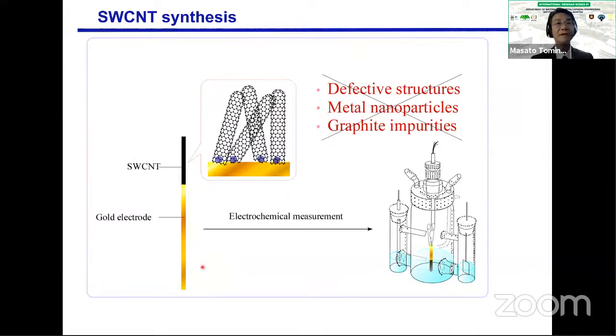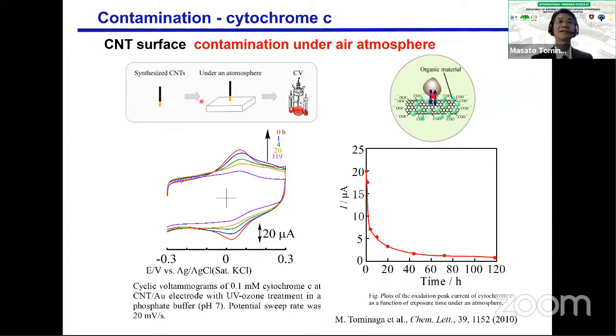In our electrode, we also use metallic nanoparticles, but these metallic nanoparticles are incorporated in the single wall carbon nanotubes. It means this metallic nanoparticle is not electroactive because this nanoparticle is inside the carbon nanotubes. So we do not care about defect structure, metal nanoparticles, graphite impurities. And then we investigate the contamination under the air atmosphere. So we use fresh carbon nanotubes. We can obtain a very nice redox wave of cytochrome C.